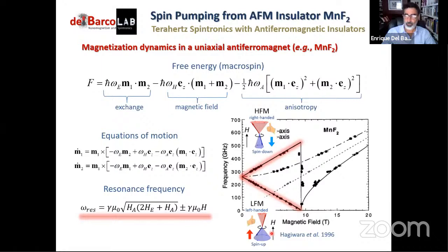And this splitting is linear, as you can tell here, until we get to a point that is known as the spin flop transition, in which the magnetic field is strong enough to make the two sublattices go perpendicular to the magnetic field, right? And beyond that, we talk about the quasi-ferromagnetic mode. So the system starts behaving as a ferromagnet somehow.